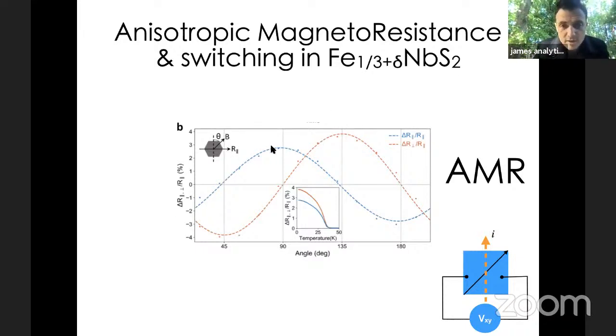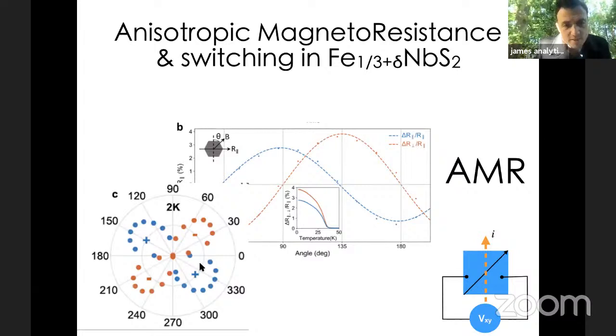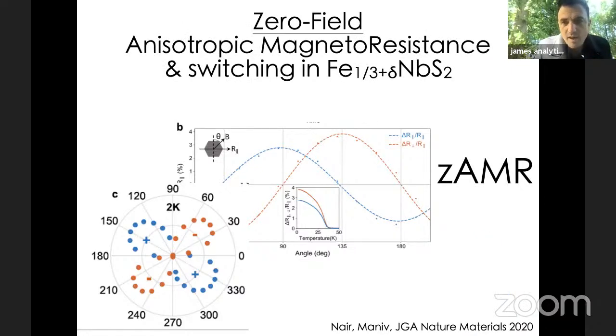And you can see that you get this very nice sinusoidal-like behavior, which is basically telling you that you're able to change those domain boundaries so you can see the changes in the anisotropy of the conductivity tensor. And you can plot this in a polar plot, to show this angle dependence directly. And what we found is that, well, I'll skip this part.